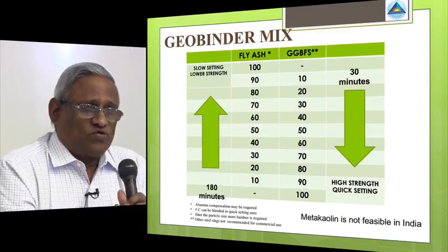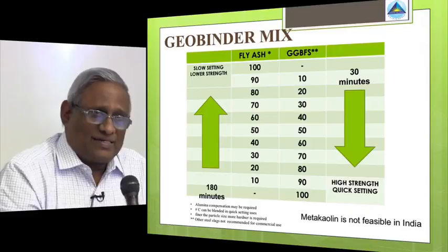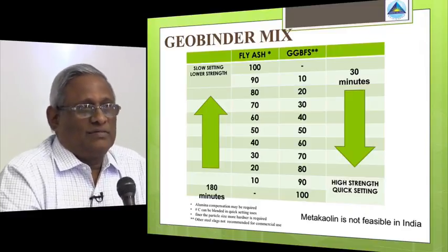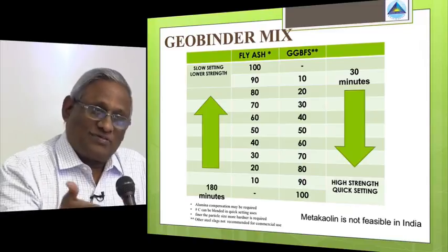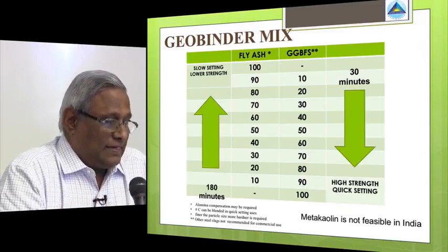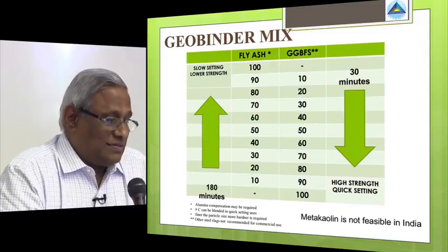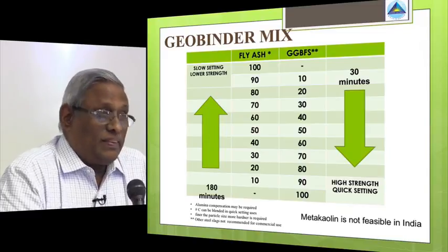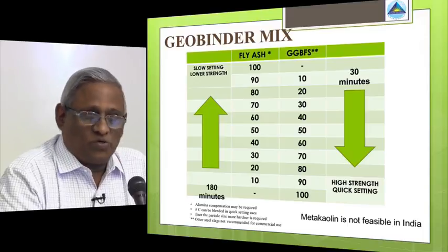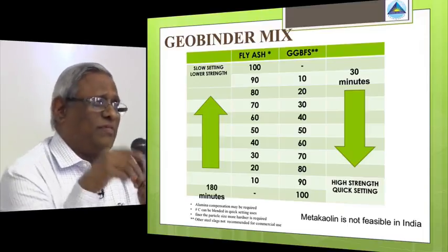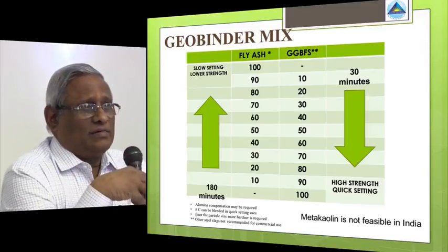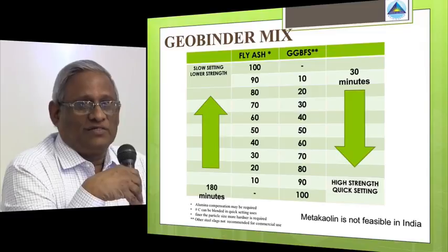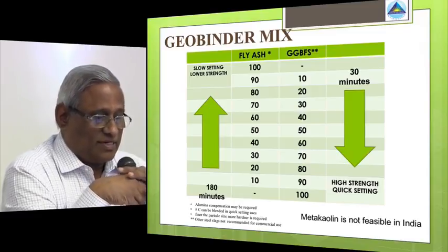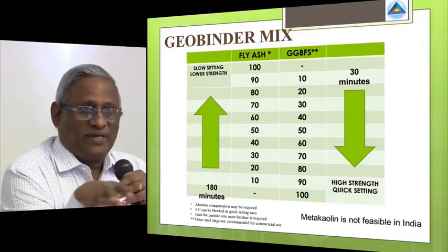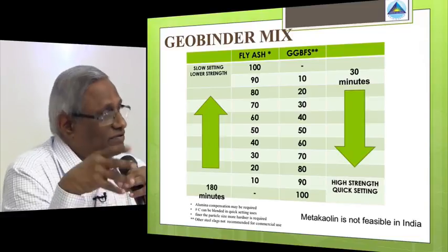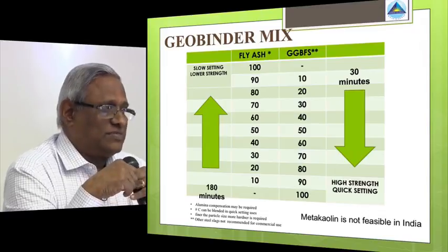Even the Class C fly ash can be used for quick setting, but it should be used on site, and it's not a commercial proposition, but if you want to do your own job, Class C you can use. And as I told you, the finer the particle size, you need more hardener. And we prefer the blast furnace slag. The other slags we don't prefer because you don't get them regularly, and you can't sell them commercially. So the blast furnace slag is one product where we can sell commercially. We don't use metakaolin because it's very expensive in India, and we cannot sell a good product. We can make one, but we cannot because it's about 3 to 4 times expensive.